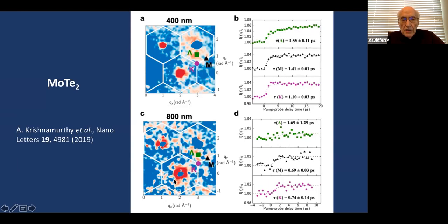Here's an 800 nanometer laser, and this is what's seen in diffraction, and here are those lifetimes over here. So you can see they're a lot shorter lifetimes than up here. So you can get around and measure those. This is all real new stuff. You see, this is 2019 work. That's just barely pre-COVID, right? So it's relatively new work.